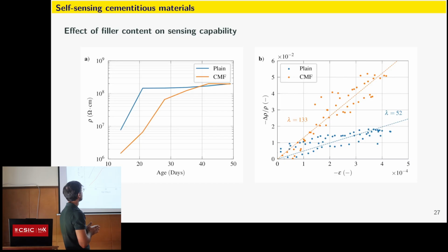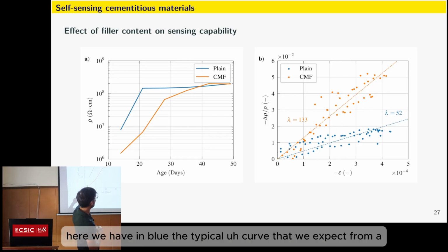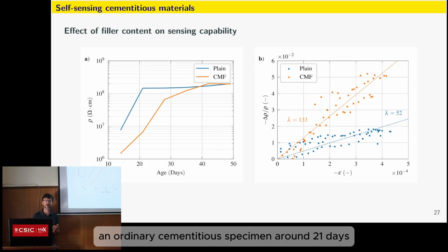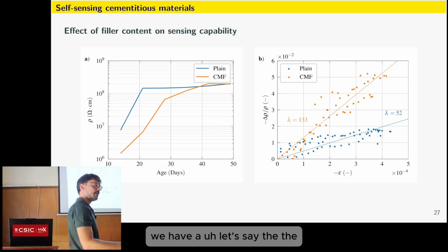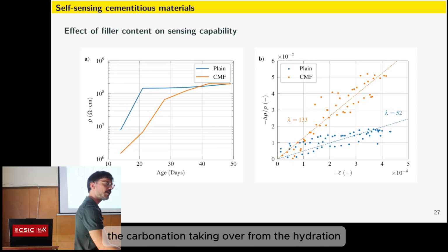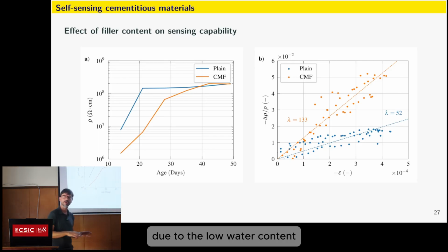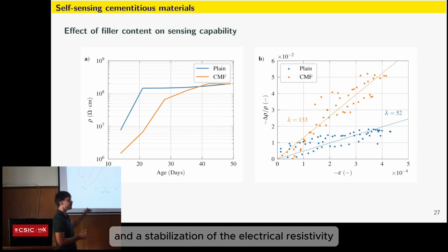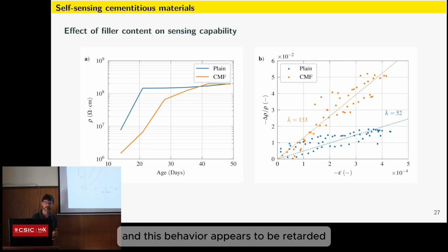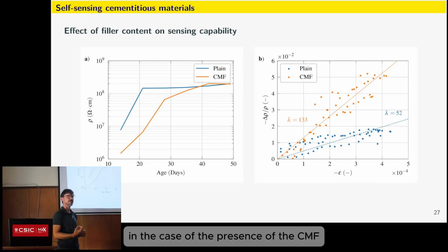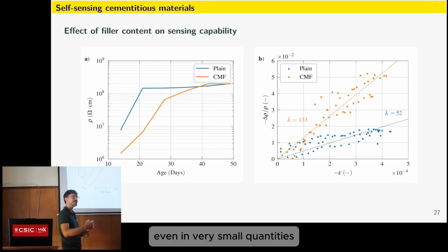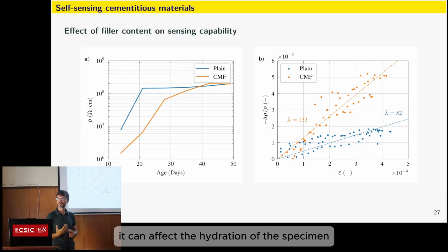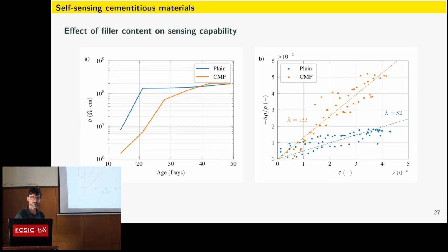Here we have in blue the typical curve that we expect from an ordinary cementitious specimen. Around 21 days, we have, let's say, the carbonation taking over from the hydration due to the low water content, and a stabilization of the electrical resistivity. And this behavior appears to be retarded in the case of the presence of the CMF. Even in very small quantities, it can affect the hydration of the specimen. So we need to keep this in mind.